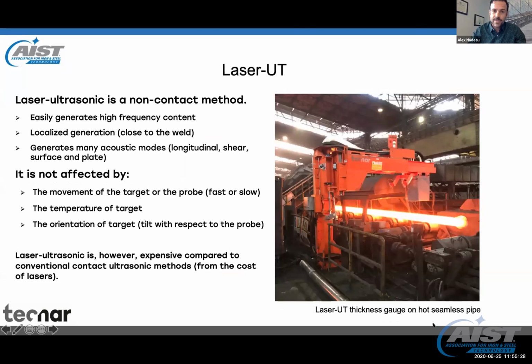Now, the other topic, the other UT technique that's been there for quite a while is laser UT. So laser UT has been invented in the 60s. It's been industrialized in the late 90s. And it's also a UT technique that's non-contact. So basically, we just focus the laser on the surface to generate sound. It's a pulse laser, and we listen to any echo coming back with a second laser,